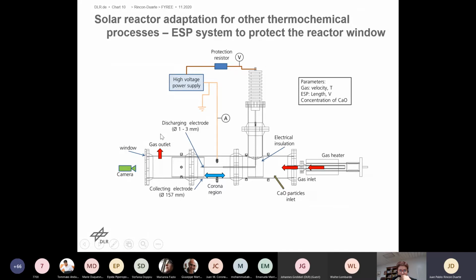For that, we designed this experimental setup, where mainly we have this tube, which is divided into three parts. In this first part, we have the inlet for the hot gases and the solid particles, as well as the inlet for the high voltage, which is provided by this high voltage power supply and transmitted through this rod, which is connected to the electrode. All these parts are electrically insulated in order to control the discharging region in our high temperature ESP. The gases leave from the top side of the tube, and in the front part we have a window to observe what is happening inside and also to evaluate the performance of this system.